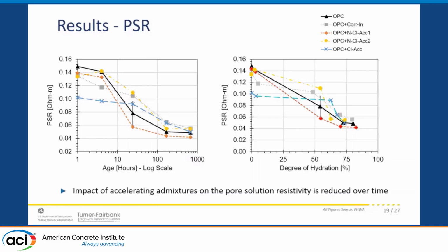It was really interesting to see, for example, the blue line is the calcium chloride accelerated admixture. At the very early age, it decreases the resistivity - we're putting all these chlorides in the solution, dropping the resistivity - but over time it actually has the opposite effect and increases the resistivity, and by 28 days it's very close to the control. At the very early ages, we notice up to 35% difference from the control, and by 28 days that difference reduced to less than 20%.